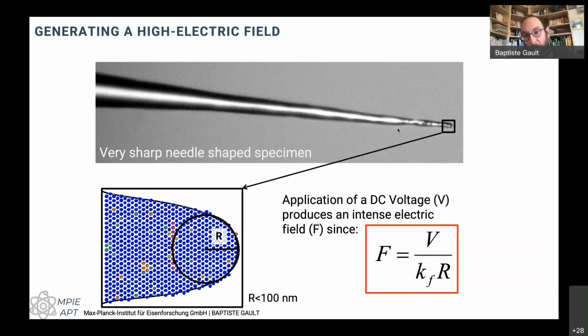The problem is that it's much harder to prepare a specimen from a very specific location within the microstructure. If you're interested in a distribution of precipitates that are more or less homogeneous across the entire microstructure, then electrochemical polishing works. The setup costs whatever an optical microscope and a loop of stainless steel cost, and it's fairly simple to put together. A good FIB is harder to get by. It costs money, and it takes a bit longer to prepare specimens.